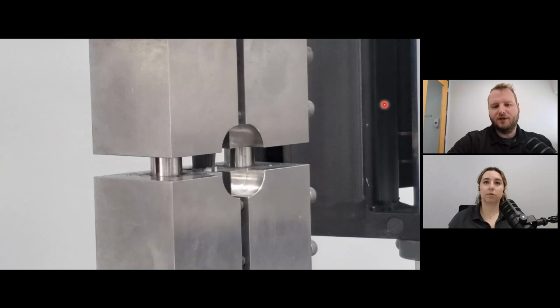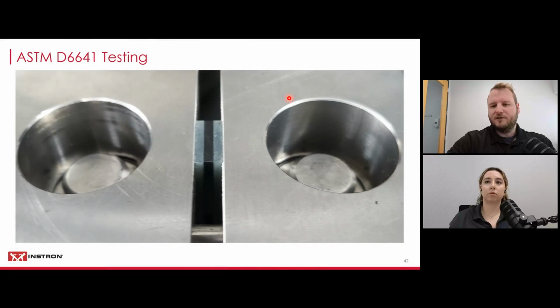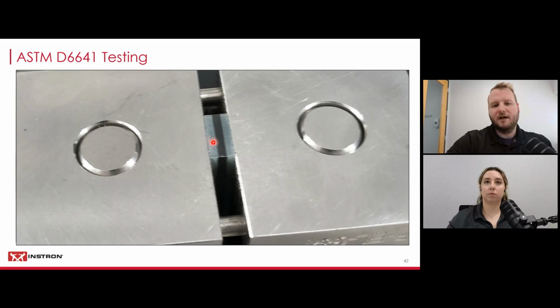That's how that looks when you run an ASTM D6641 test. It's very important for a successful test, or it's actually required in the testing standard, that the specimen ends do not crush when the specimen fails. This could indicate that the specimen preparation was improper, and it's very important that the ends of the specimen are machined flat and parallel to each other, and they need to be as perpendicular to the loading axis as possible, really. And you can see here, this is one side of the specimen after the test. The ends did not crush, and then this is the other end where it also didn't crush.